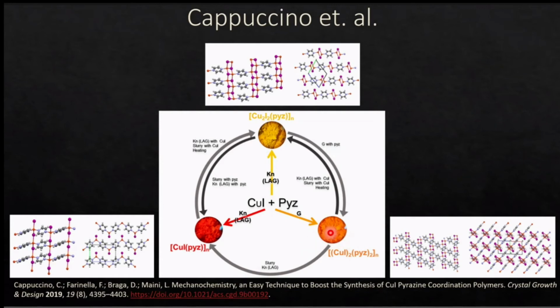They also looked at interconversions between these polymorphs and found that you can actually go between yellow, orange, and red, but what you have to do in order to get from red and orange up to yellow is to add energy. And what that indicates is that the yellow is a higher potential energy than the orange or the red. And so that indicated something about the thermodynamic relationships between these polymorphs, and we were able to start to track and trace out the relationships and how these were interconverting from Cappuccino et al.'s work, which was amazing.